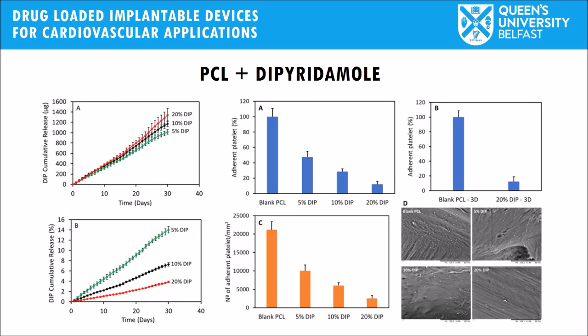Additionally, we can see that these materials were capable of providing a really sustained delivery of dipyridamole. We tested it for 30 days, but the percentage of the total content in the graft was only, at the maximum loading, 2% of the loading. Interestingly, there is not a massive difference in the amount of dipyridamole released from these grafts, considering that the initial concentrations of drug in the graft were different.